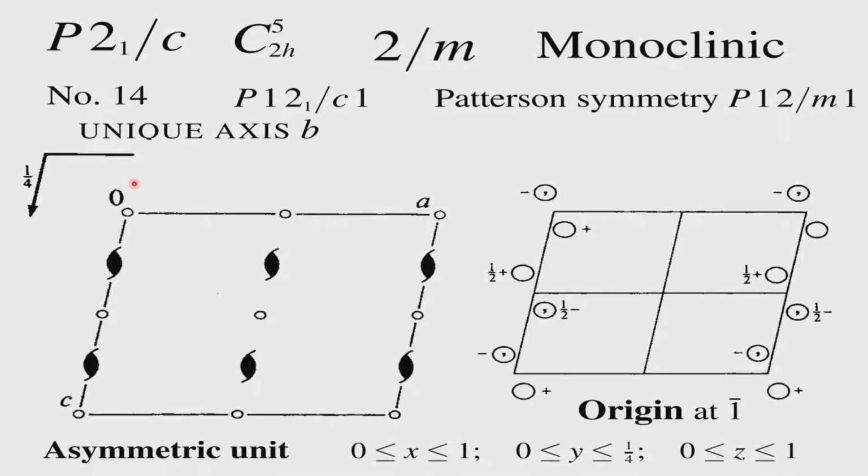Therefore, we see that the two-fold axis, screw axis and the glide planes are shifted by 1/4 and 1/4. This is shifted 1/4 perpendicular to that, and this is the nomenclature which we learnt long ago in the earlier classes, and this is the 2 1 screw axis, which is now appearing at the 1/4 position. So, if this diagram is given again and nothing else is given, is it possible for us to guess the space group?